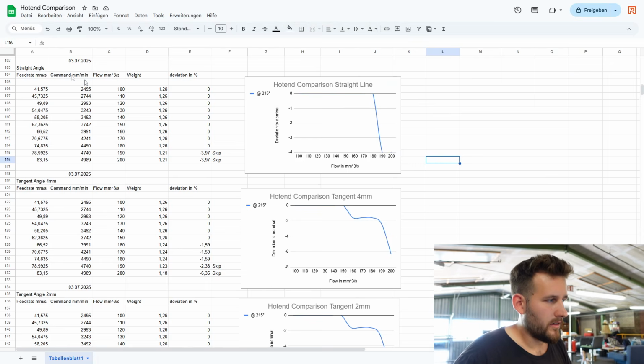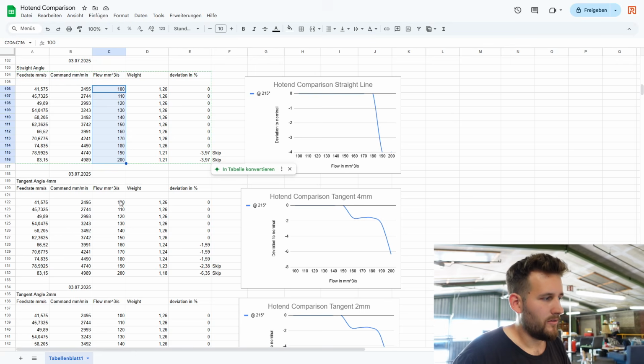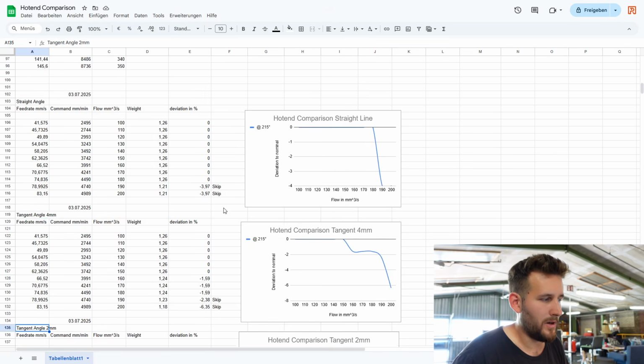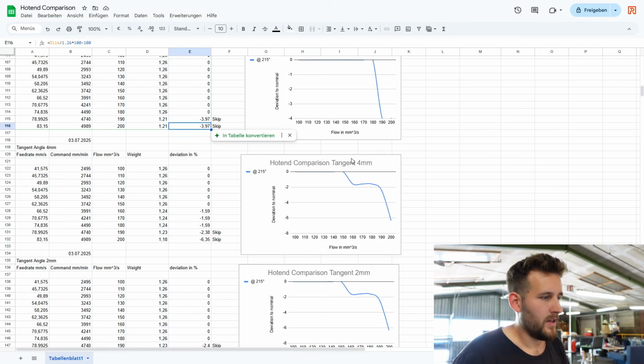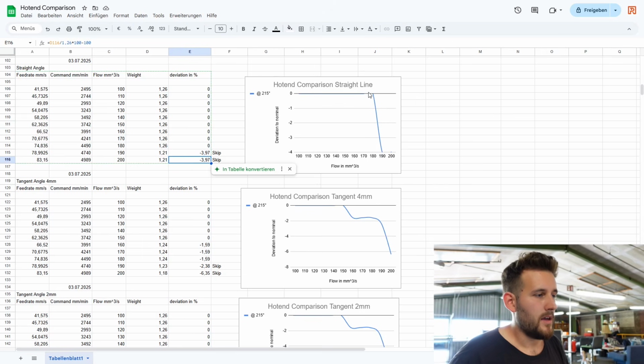And yeah, as you can see here, these are the results from 100 cubic millimeters to 200 for each of these 3 Hotend tests. This is the straight angle, this is the tangent angle in 4mm, and this is 2mm. And yeah, here are the results that are being weighed. So 1.26 grams is pretty much the nominal, and here I got the deviation from nominal. I don't really have tested this setup before. It is really performing quite well in terms of flow and pretty much matches my expectations when it's just from the calculation side. Aluminum with its heat transfer, etc.